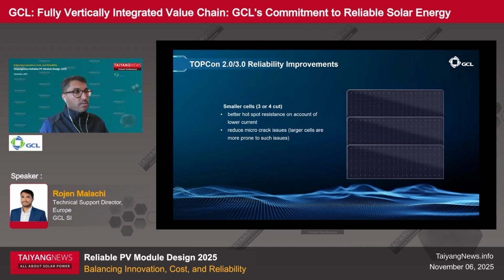This has two important reliability benefits. First is the operating temperature and current: the lower operating current significantly improves hotspot resistance. Low current means that if a portion of the module is shaded or stressed, local heating is minimized and hotspot formation is much less likely. Second, smaller cells greatly reduce the risk of microcracks and slow crack propagation. Large format cells are mechanically more fragile and cracks can spread faster across a large silicon area. By reducing the cell size, we distribute mechanical load more evenly and increase module resilience to transport stress, installation stress, wind load, and thermal expansion.